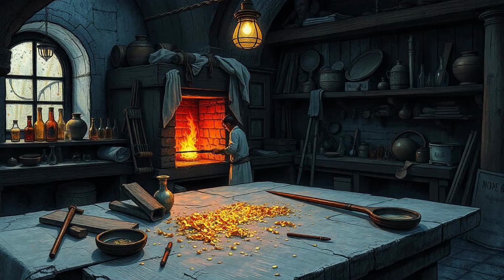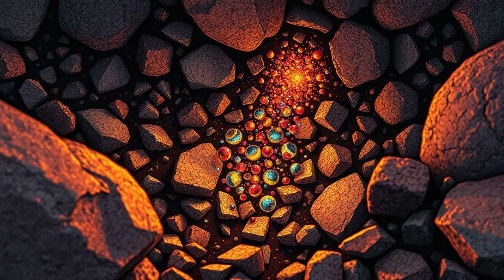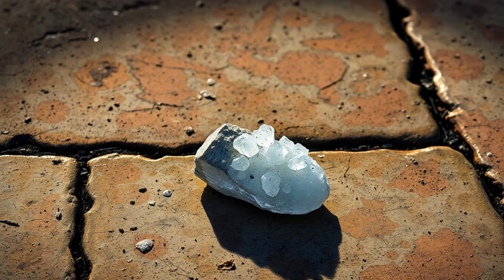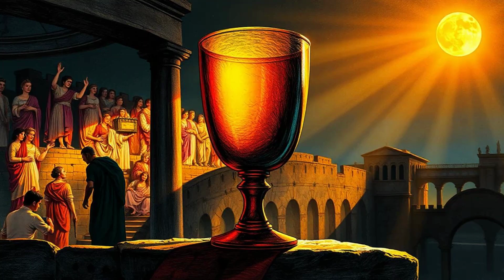What they found was astonishing. The Roman glassmakers had somehow infused the glass with microscopic particles of gold and silver. These particles were unbelievably small, only about 50 nanometers in diameter. That's less than 1,000th the size of a grain of salt. They had created what we would now call a nanocomposite material. This is the secret to the cup's color changing trick.